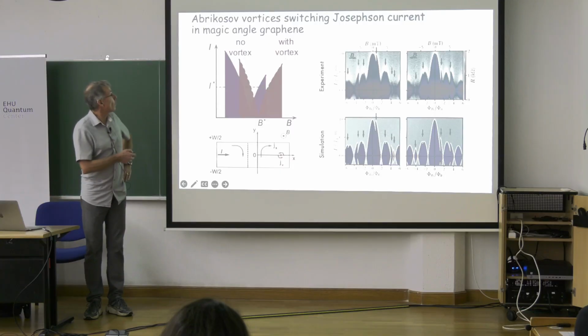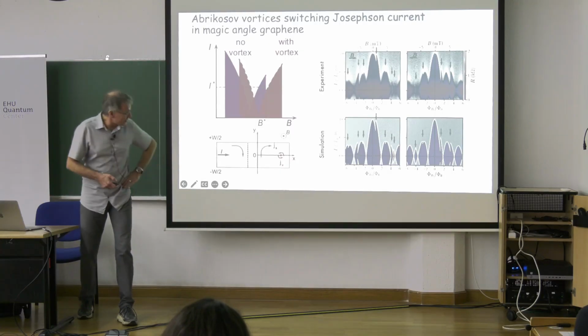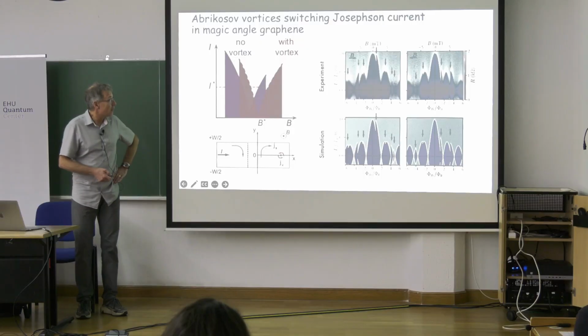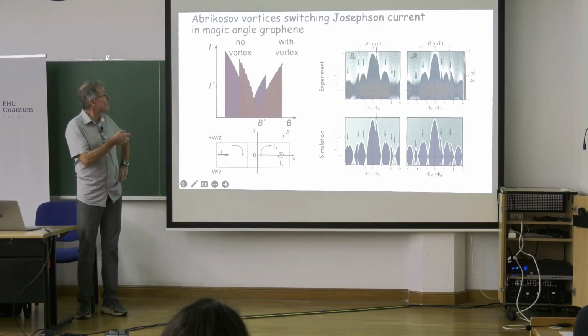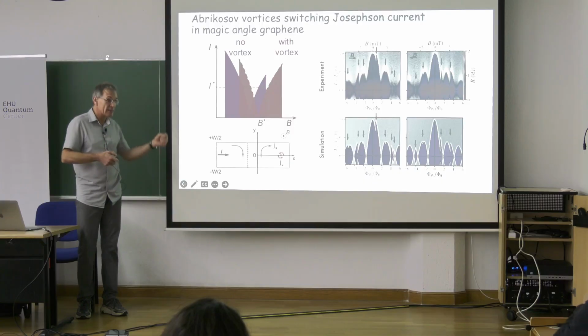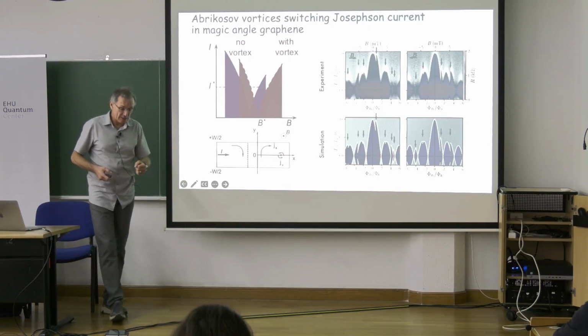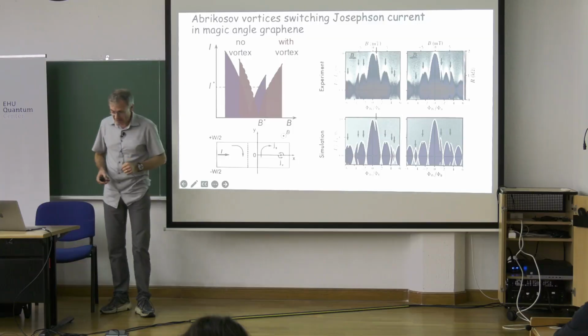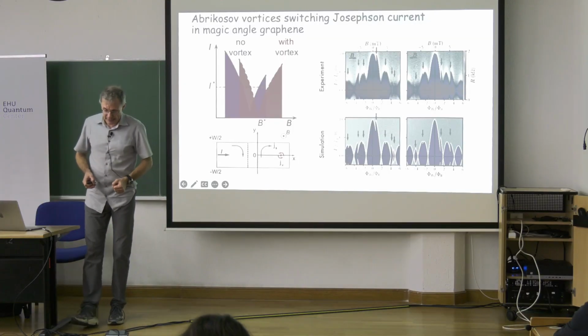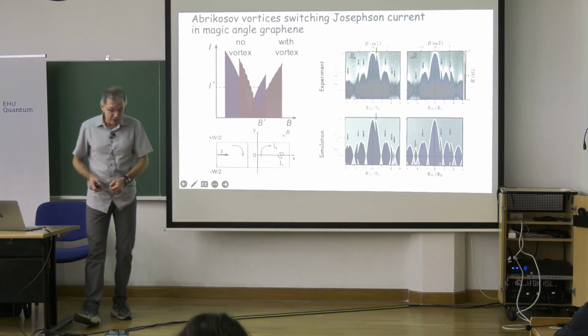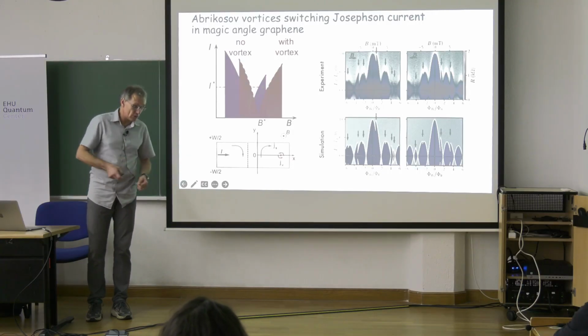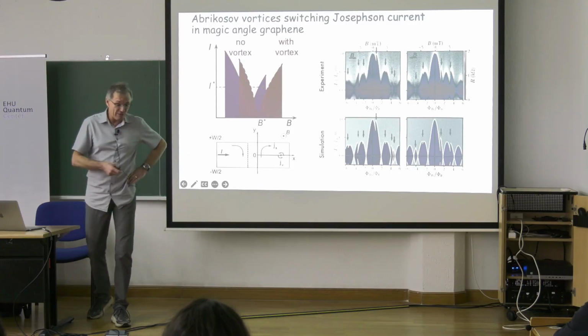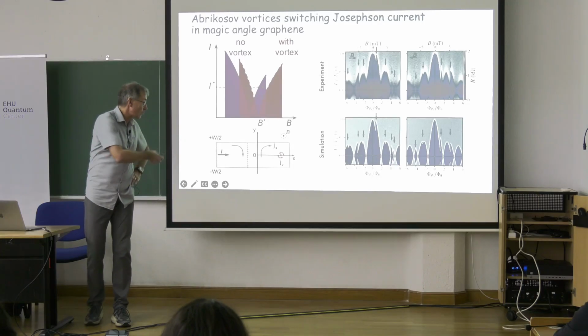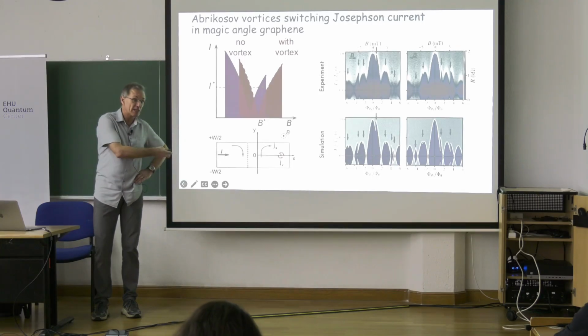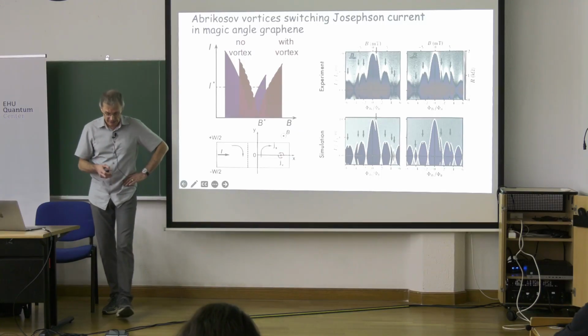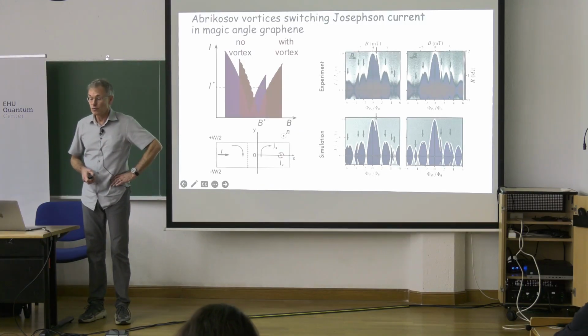So, that's the summary of what we did: because vortices can switch the current in a Josephson junction made in graphene, one can use the Josephson effect there to learn about the properties of vortices in graphene, and in particular one can also extract the superfluid density and other things which are otherwise rather difficult to get.